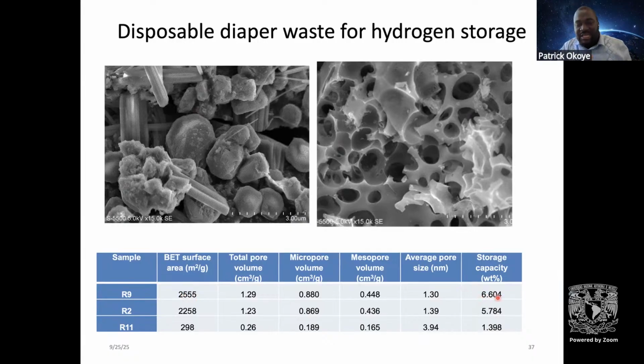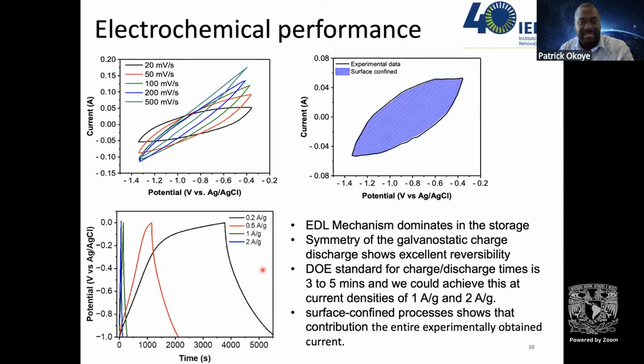The previous DOE, that is Department of Energy United States, capacity is about 5.5, although it is now reviewed to about 8 or 9 weight percent. But we were able to exceed those previous standards, with 6.604 weight percent of hydrogen stored in our material. The worst sample here, of course, stored far less than that.